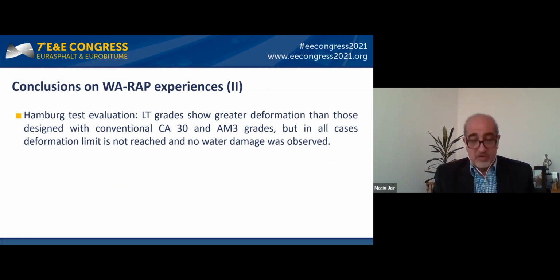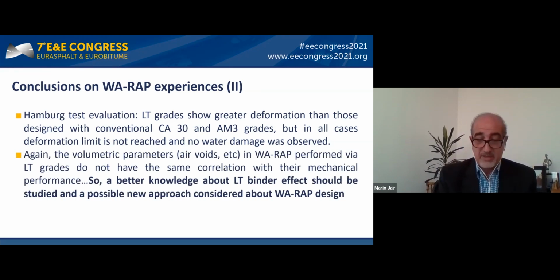With regard to Hamburg test performance, the use of low temperature grades showed greater deformation than those designed with conventional CA 30 and AM3 grades. But in all cases, the deformation limit is not reached and no water damage was observed. And again, the volumetric parameters, air voids, etc., in warm RAP performed via low temperature grades don't have the same correlation with their mechanical performance. So a better knowledge about low temperature binder effects should be considered, and a possible new approach considered as well about warm RAP design.